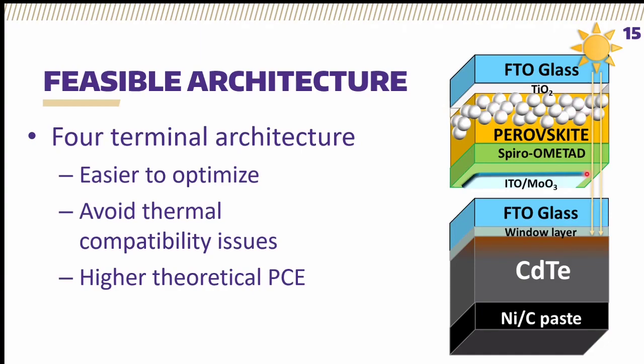The third thing that I haven't mentioned yet is that in order to use this type of architecture, we have to go away from the super high efficiency perovskite devices that people have used in the past and move to these wide band gap bromide-based devices. In this case, methylammonium lead bromide is the perovskite, which means that the 20 to 25% efficiency you may know perovskite solar cells normally achieve cannot be achieved in our top cell, which only has a world record efficiency of 11%.